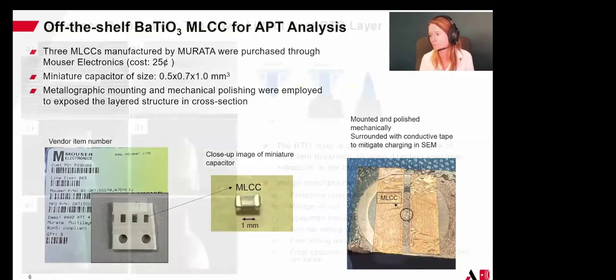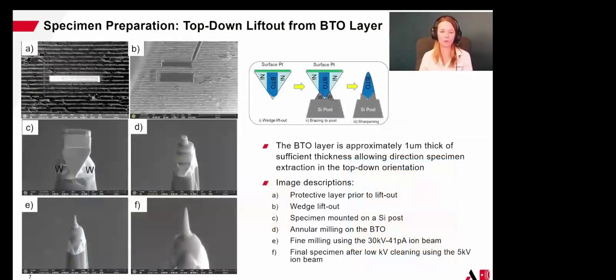So sample prep is obviously so important both for electron microscopy and atom probe, and we can approach sample preparation of MLCCs in a couple of different ways. And there's some unique considerations for these type of materials. As you can see from the surface, here we have in this top image A, those bright regions are our nickel-based electrodes, and those darker regions are the ceramic material.